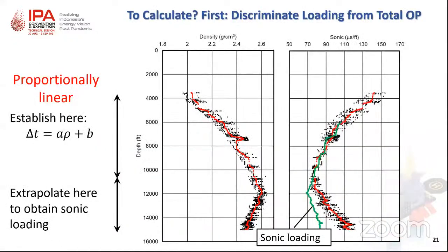And as mentioned in the theoretical background, it is possible to construct sonic response to loading from density log, since density log is unique for loading mechanism. Also, as mentioned, the relation between sonic and density is linear in the loading section. Here, we are certain that down to the depth of 10,500 feet in the hydrostatic zone, there is no unloading effect. We can then establish a linear relation in this section and extrapolate the equation into the section below to obtain sonic response to loading. By applying these techniques, the resulting sonic response to loading is shown in this green color.